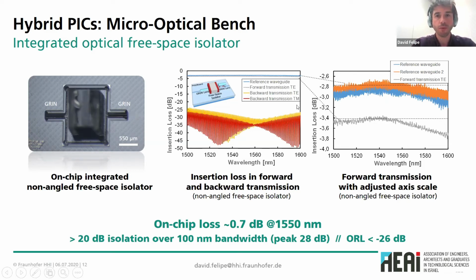And some of the key performance indicators of optical isolators are shown here in this graph. Basically we achieved on-chip losses of under 1 dB at 1550 nanometers, and peak isolation of 28 dB in the C-band, with isolation of more than 20 dB along all the wavelengths of the C-band. So this shows that with this fairly simple concept, we can implement crucial components in photonic integration, such as optical isolators and circulators.